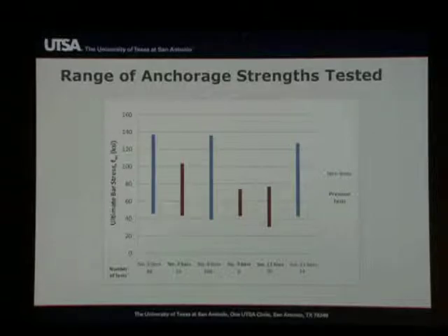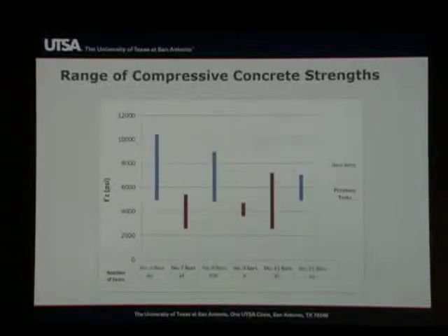We see that there have been a significant number of tests added in the range of number 11s, number 8s. And then, of course, we're looking at strengths that go all the way up. These were going to be grade 100 and grade 120 bars that can go well in excess of 100 KSI. And if you look at the previous range, most of the work done in number 8s and number 11s got up to maybe a maximum of 90 KSI, significantly below what this study has done. And if you look at the number 7s, we did have a little bit more of a wider range. And this one, I apologize, is just repeated.